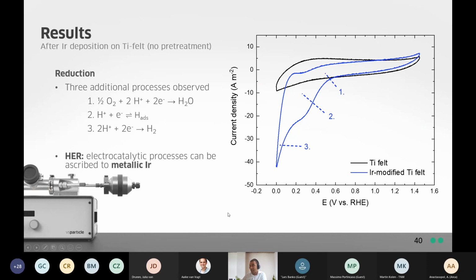If we then compare this to a CV plot of the material after iridium has been deposited, what we see here is that we get three characteristic reduction processes. The first one being the reduction of oxygen to water. The second one being the reduction of hydrogen ions to hydrogen atoms. And the third one being the reduction of hydrogen ions to hydrogen gas. And what this shows is that after depositing our iridium on the titanium felt, we were able to prepare a hydrogen evolution reaction electrocatalyst. And this confirms that we've indeed deposited metallic iridium on these felts, because those are active for the HER reaction.